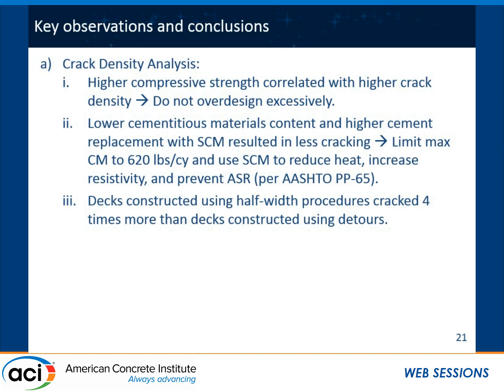Decks constructed using half-width procedures cracked 4 times more than decks that were constructed using detours. So if possible, the full width should be the preferred approach. Decks on steel girders appear to crack more, and we'll keep it just as that.